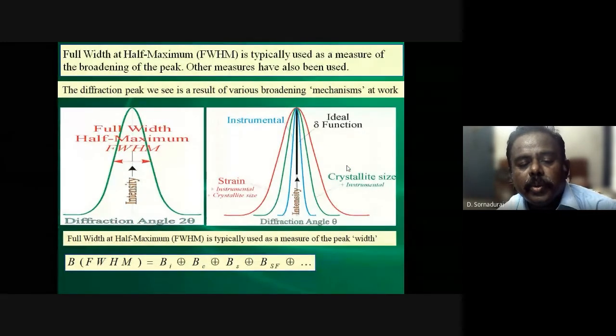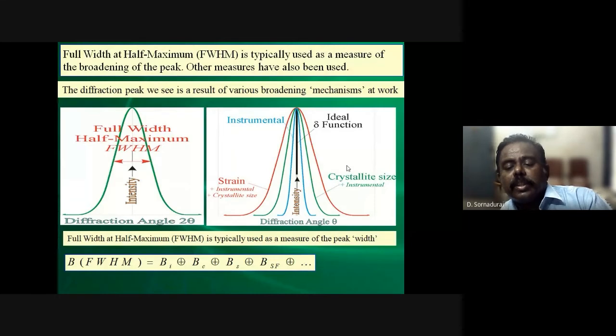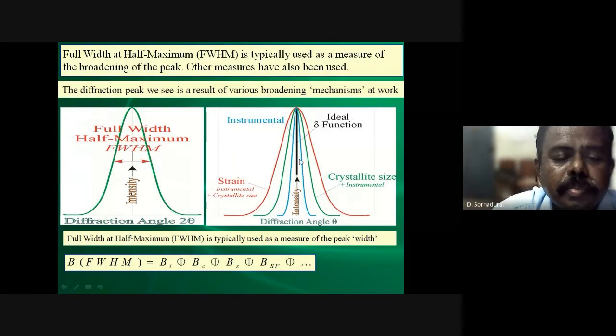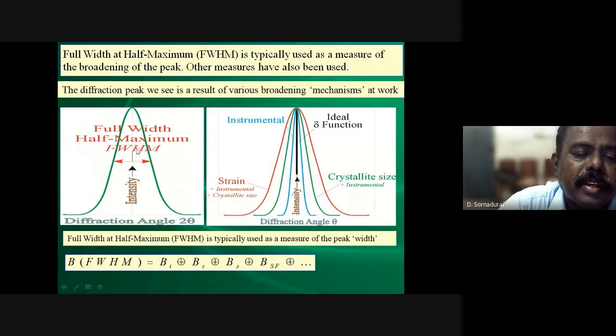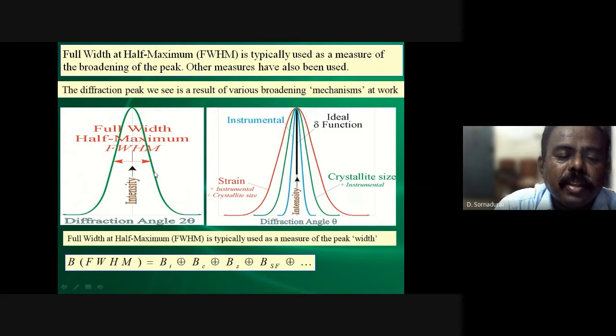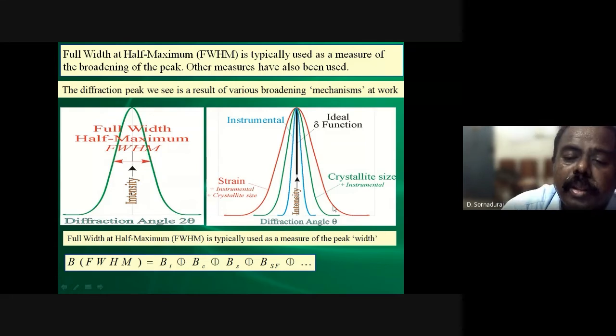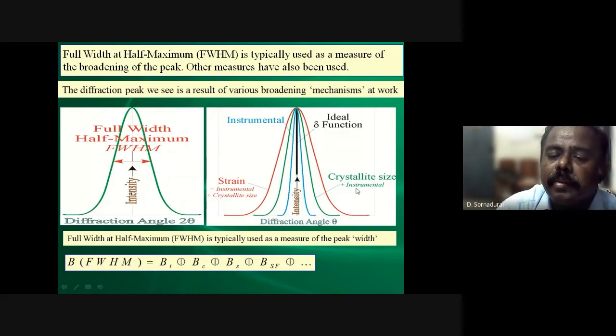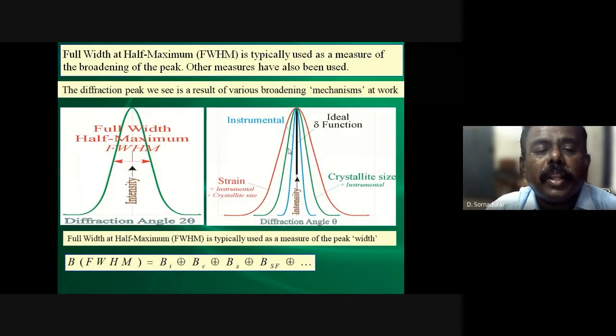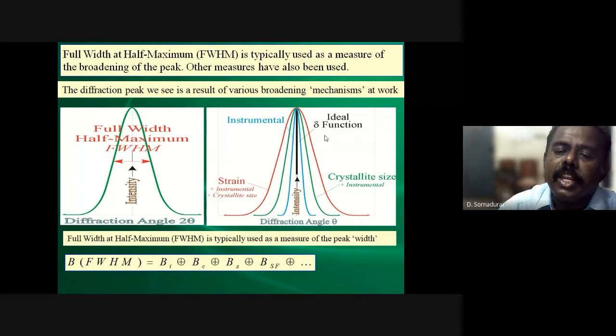So here you can see how the full width at half maximum varies with respect to different things. The left side is the diffraction angle, and then the intensity and full width at half maximum, and this is actually fitted by several functions. Okay, for example, this is a perfect delta function, the red one is the obtained peak actually, and this green one is the crystallite size effect, and this light blue one is the instrumental effect. Okay, so the diffraction peak which we see is a result of various broadening mechanisms at work.